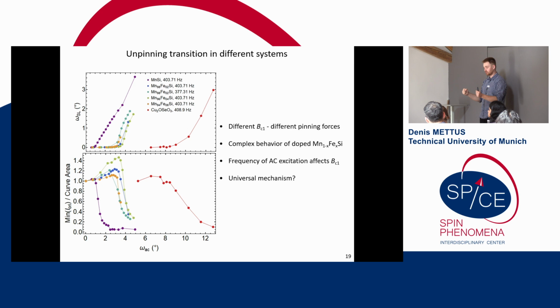When you shake the sand a little, it can help your sand to order a little bit more. So in this way, we apply an AC field, but we don't move the skyrmions, and the little shaking helps skyrmions to overcome some pinnings and order more into the lattice, hence giving the increase of the intensity.